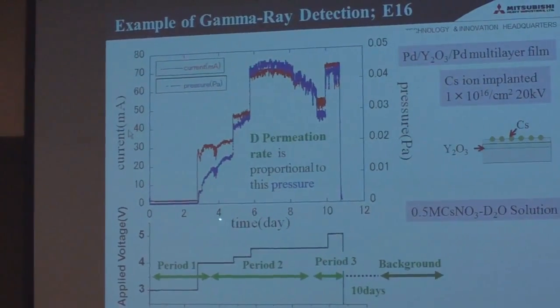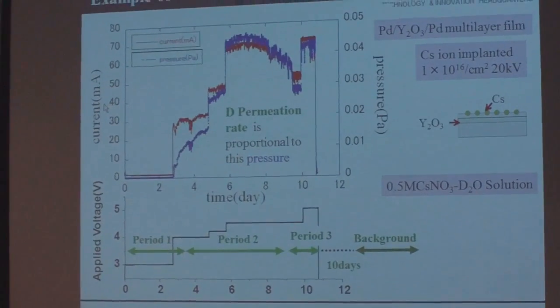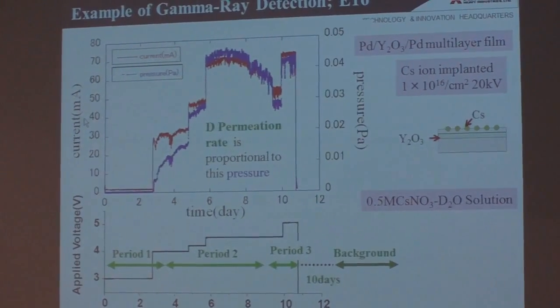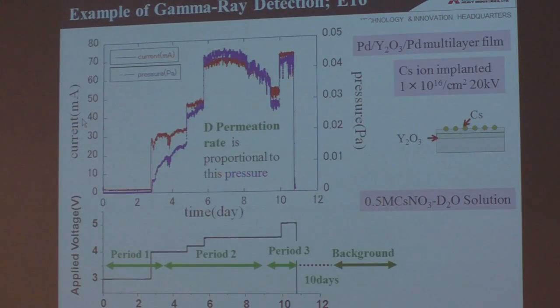There was a question regarding the deuterium flux through the membrane. You have vacuum on the other side. Yes. When you are increasing the voltage, you are increasing the pressure, so you are supposed to increase the permeation. Isn't it affecting the vacuum side, so that you can sense an increase in pressure, a lower vacuum rate? This is the pressure on the vacuum side. The green and blue correspond to the pressure, so it corresponds to the flux. What is the vacuum rate? The vacuum is here, about 0.02 Pascal region.